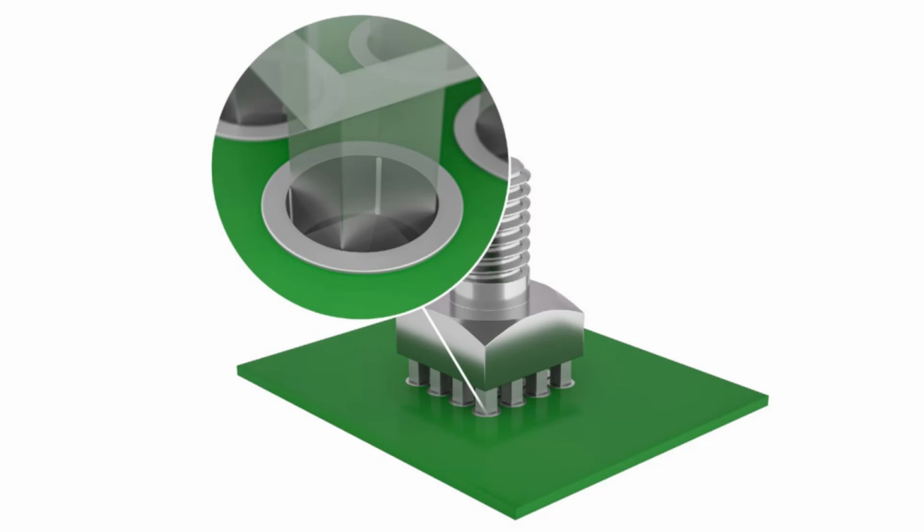In terms of long-term reliability, the REDCUBE press fits surpass a surface mount technology, or SMT, solder joint by up to 30 times. A single solid press pin typically requires a force of 100 newtons to extract it from a 1.6 millimeter PCB. So even a small component with 8 pins could handle the weight of an average person without being pulled out of the PCB. This makes REDCUBE press-fit terminals ideal for offering both electrical as well as mechanical connection solutions for electronic components.